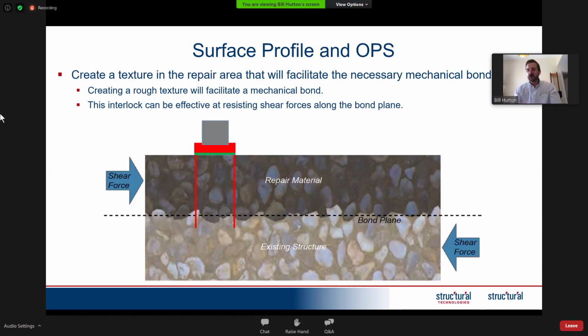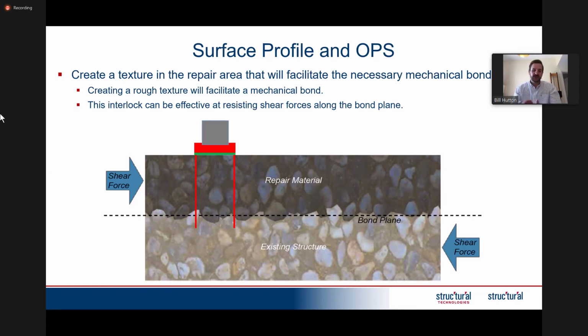But at the end of the repair, once it's finished, often a test which is done is called a pull-off test. That's where you're checking the bond strength between the repair material and the native concrete. So here you would core down through the repair into the existing structure. Then you epoxy anchor a dolly on top, and then you pull that off. You want to check that the strength required to break the concrete is higher than the strength required by your design. As a rule of thumb, it's typically maybe 1.4 MPa.